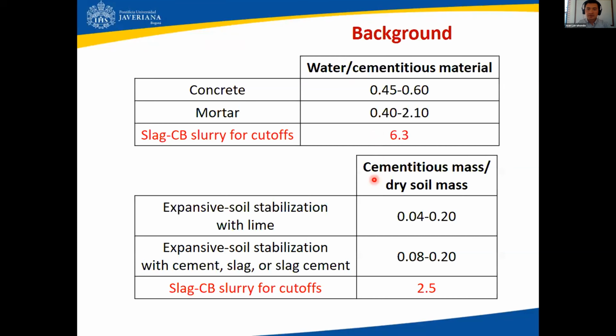Now, the second number I want you to look at is the ratio of cementitious mass, that is either Portland cement or Portland and slag, divided by the dry soil mass, that is bentonite. And these numbers are very important because there is a lot of evidence, a lot of studies and research evidence from the field of expansive soil stabilization, swelling soil stabilization, for example, with lime or with cement, slag, or slag cement. And these numbers are in the order of 4 to 20% overall for this type of expansive soil stabilization. And I'm going to be talking about these types of methods to support the discussion of my research.